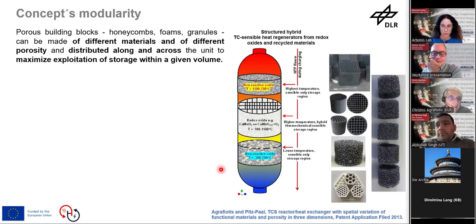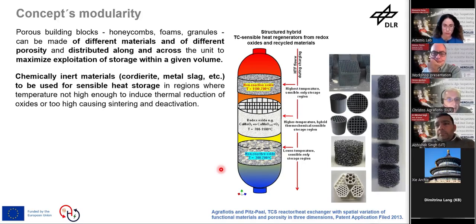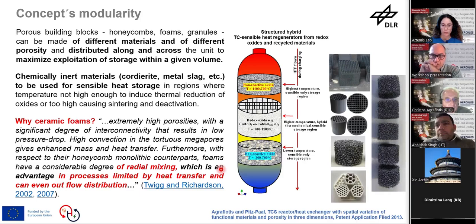And by this, if we click once or twice more, we will see that we can also add to these redox materials sensible-only materials, chemically inert materials like bricks, cordierite, or metal slag, that can be used for sensible heat storage, like the bricks we saw in the first slides, in regions where, for instance, the temperature is not high enough to induce the reduction-oxidation reactions, or where our redox materials are too sensitive and suffer sintering and deactivation.